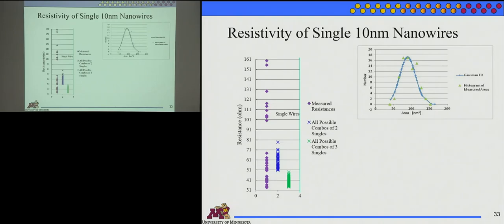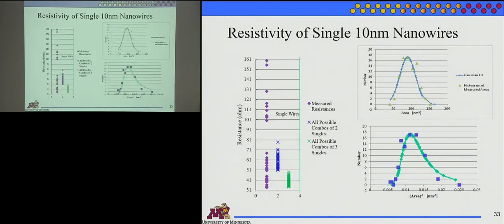So when you're measuring resistance, it's resistivity times L divided by A, right? So we shouldn't get a Gaussian distribution. We should get an inverse Gaussian distribution when we're measuring resistance, which would give you a highly probable low value and a high value tail, kind of like we're seeing in our data. So Nanoletters said that was fine. They'd go ahead and accept that. And it went through a little more than that, I'll say, but eventually it is published now.